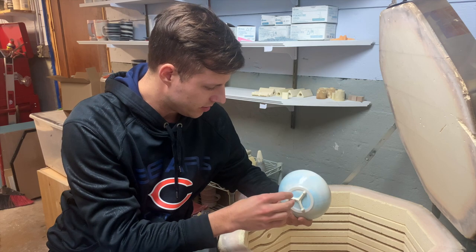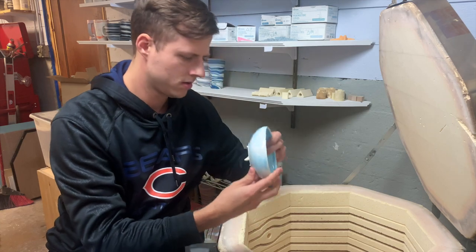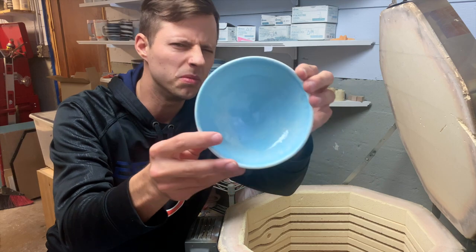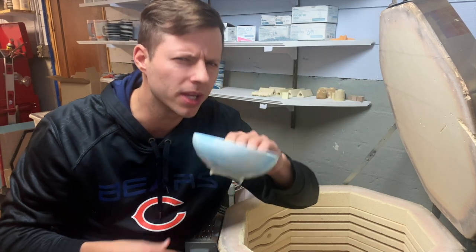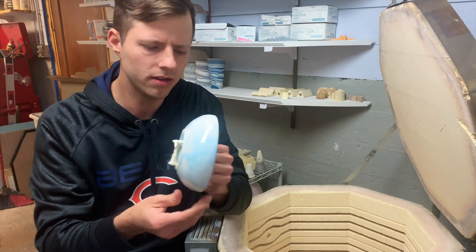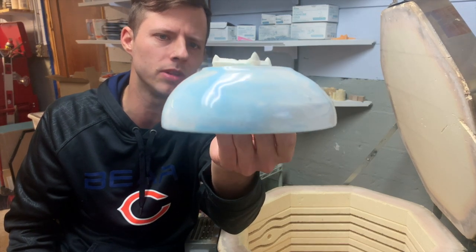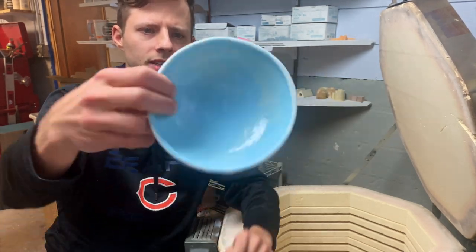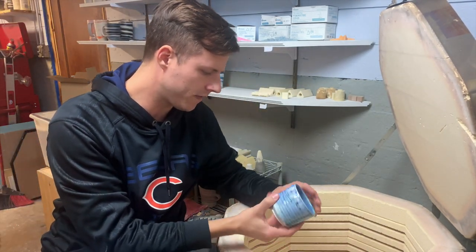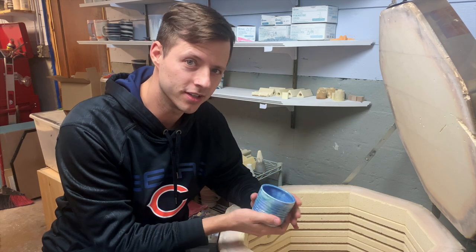It ran a lot — I'll have to knock that off. This was blue outside, blue inside. Probably too much application. We've got to work with her on application of glazes. This is the Amaco Persian base — probably not enough as well. Maybe she layered it though. That's what it was — it was a clear, white-ish opaque glaze with blue on top. She wanted blue and green.